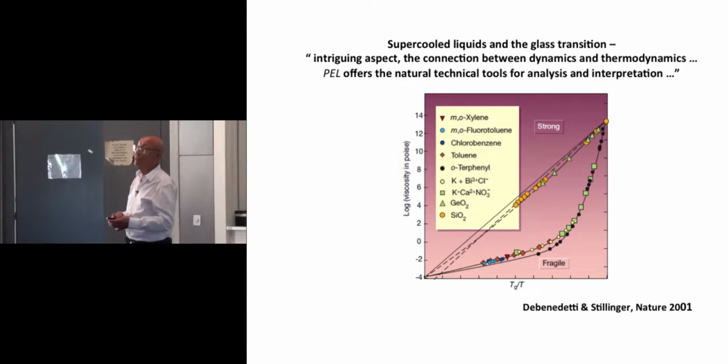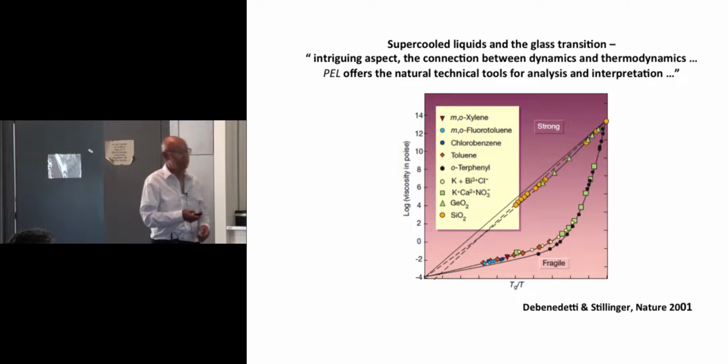You can replace the word dynamics with kinetics if you like, because that's what we saw. Mechanical melting versus thermodynamic melting. One is thermodynamics, free energy based. The other is kinetically based, because it has to do with the mechanism of vanishing of shear instability. So that kind of thinking carries over in the glass problem as well.